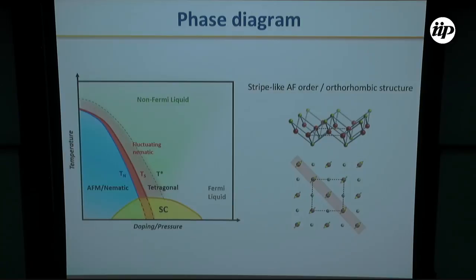We also saw this phase diagram yesterday. So this is a schematic phase diagram for this kind of materials. The parent compounds are antiferromagnetic at low temperatures. They show this kind of stripe-like antiferromagnetic order. They also have an orthorhombic crystalline structure and a sort of electronic order, which is named nematic in analogy with liquid crystals. So when we dope these systems, superconductivity emerges, often with the highest critical temperature close to the point where this order goes to zero at zero temperature. And that's why often we talk about quantum critical points and the effect of quantum criticality in these materials.